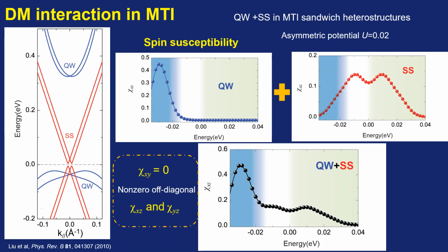So we calculate, because this kind of magnetic TI film breaks the mirror symmetry with respect to the XY plane, so χ_xy is 0. So we just consider χ_yz. We calculated the χ_yz of the quantum well state and surface state in this kind of model. We can see for the quantum well state, it shows a peak when the chemical potential is in the valence band.